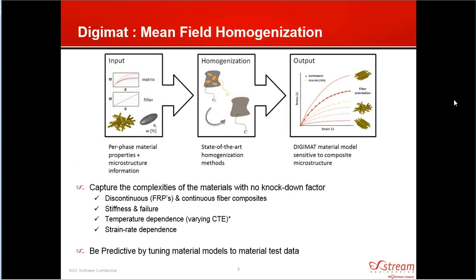So the way that Digimat handles that issue is using mean-field homogenization. And this is really the engine behind Digimat that allows us to be so accurate in our analysis of these discontinuous fiber composites. So what we do is we build our material models at a level below the traditional composite level that most people are modeling in finite element analysis. So we have a description of the matrix, so a stress strain curve for the matrix, if you will. We have a description of the fibers, and then we have a description of the local microstructure.